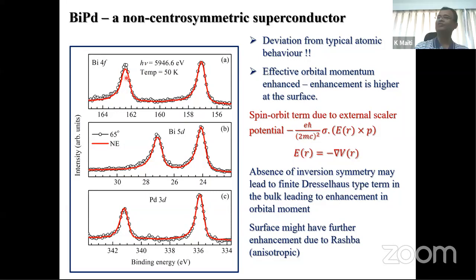But we always found that this intensity is much stronger compared to this. So this is found only for bismuth, but we don't find it for palladium. Palladium 3d shows essentially 2:3 ratio. Now, if you make it more surface sensitive, you see that this intensity goes up. Okay, so this black line is actually the more surface sensitive spectrum.